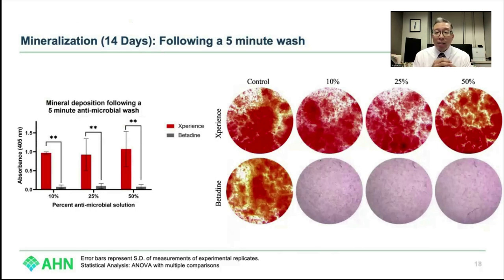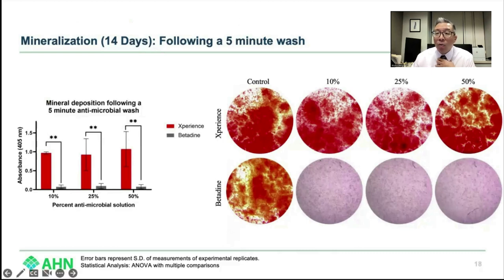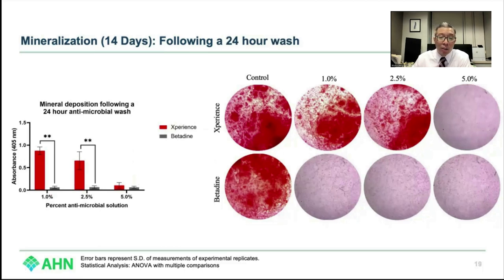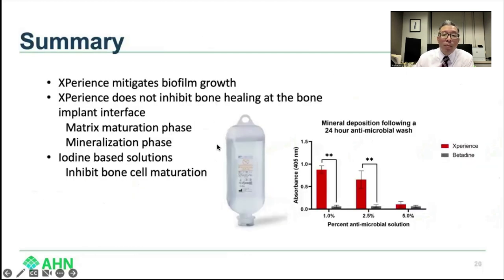This story tells itself — alizarin red being positive, with the amount of mineralization showing up in red. You can see that with Xperience, even at 50% in a five-minute wash, the amount of mineralization is dramatically different. Statistically, at all concentrations for the five-minute wash, mineralization was much greater than with betadine. At the 24-hour wash, a very similar story holds for lower concentrations including 1% and 2.5%, being statistically significantly more mineralization — and therefore an excellent reflection of what Xperience does in bone healing.